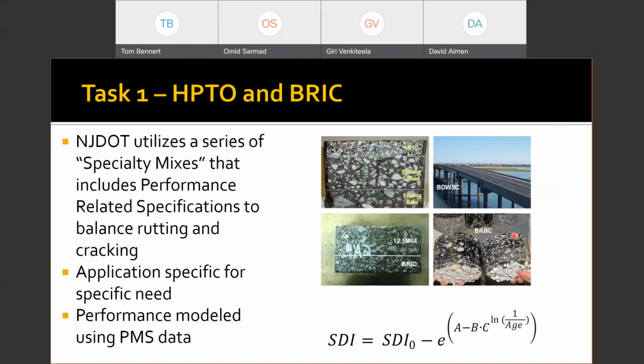Just some examples of some of the stuff that we've done. Since about 2006, what we've been doing in New Jersey is pushing the use of what we call performance-based design. And what that really means is that historically asphalt and concrete are designed based on volumetrics: how much asphalt can I get within a gradation to ensure that I also have a certain amount of air. And this is important based on historical information. If we meet certain volumetric criteria, the material should perform well. But we know that with the advent of a lot of new additives, materials, and production practices, these volumetrics don't necessarily hold. So what we've done since 2006 is develop a series of performance-based materials targeting certain areas that are critical.